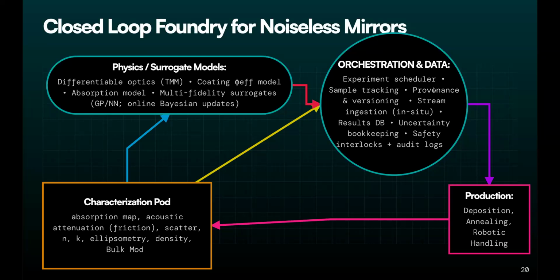And if you can do this completely robotically, and you have all the characterization in situ, you can get this 2-year cycle time down to something like 2 weeks, because the measurements don't take any time at all. So this deposition plus annealing, for sure we can get it down to a week, maybe a few days or something like that. And depending upon how many of these things you can run in parallel, you can now think about making order of magnitude improvements in the thin films that we have. I think, although, like I said, I'm not a condensed matter physicist, I may be wrong.